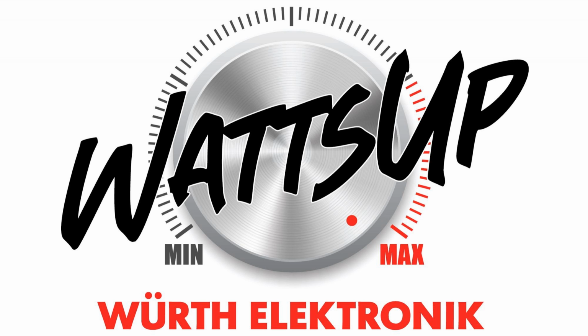The WE-TGF thermal insulation pad is great for applications where a thin interface is needed and it needs to withstand high compression forces. Next, we have Würth Electronics WE-PCM. This is a paraffin-based phase-changing material. It's going to remain solid at room temperature, and then it will enter a flow state once a temperature over 60 degrees Celsius is reached.